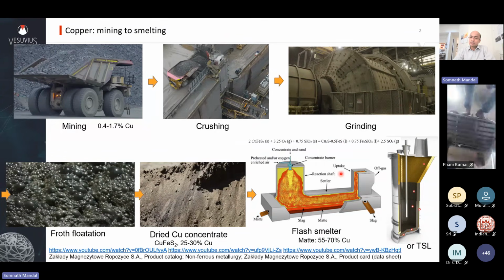It is now much deficient in iron sulfide and more enriched in copper sulfide. As a result of the oxidation of the iron sulfide portion, you have a lot of sulfur dioxide as a byproduct, which is later converted to sulfuric acid, and that acts as one of the components that goes into the electrolyte in the downstream electrolysis process.